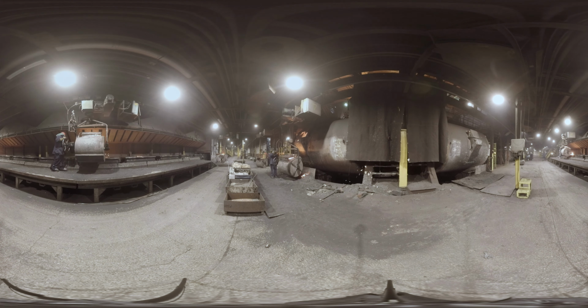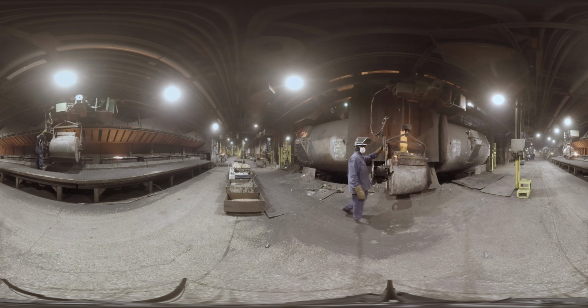So what you'll find is when he takes it away from there and he's added those things in, he takes it down to the end of the line, and you'll see often that they're taking a sampling out of there. That sampling is going in for real-time chemistry monitoring, and depending on what kind of drum we're making at the time, those chemical parameters can be tighter or looser, but we are trying to hit the same chemistry pretty much every time, because not only does that make for the correct mechanical properties of the finished component, but it also makes the thing pour better into the molds, and that's what takes out the porosity and various other things like that.